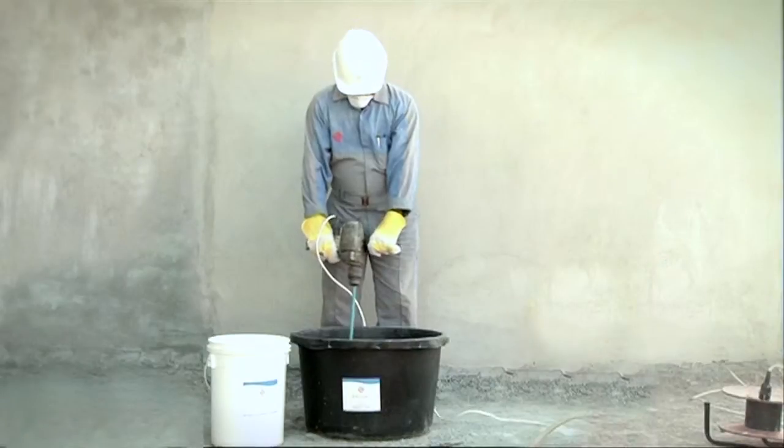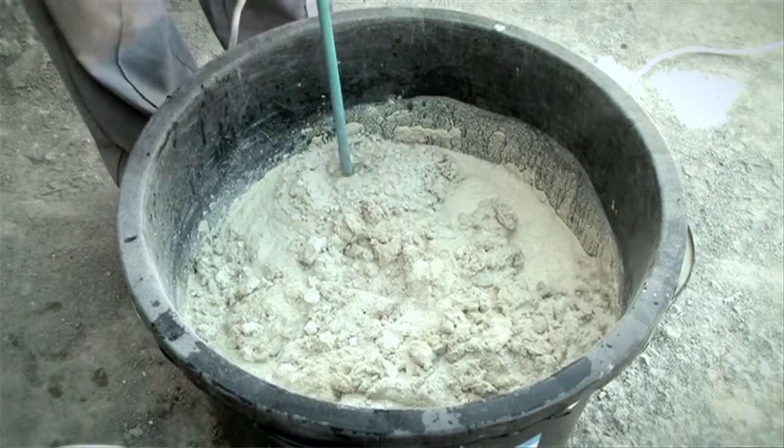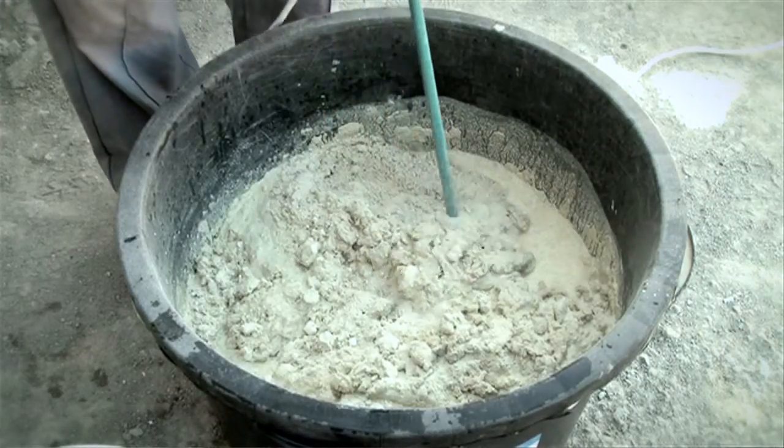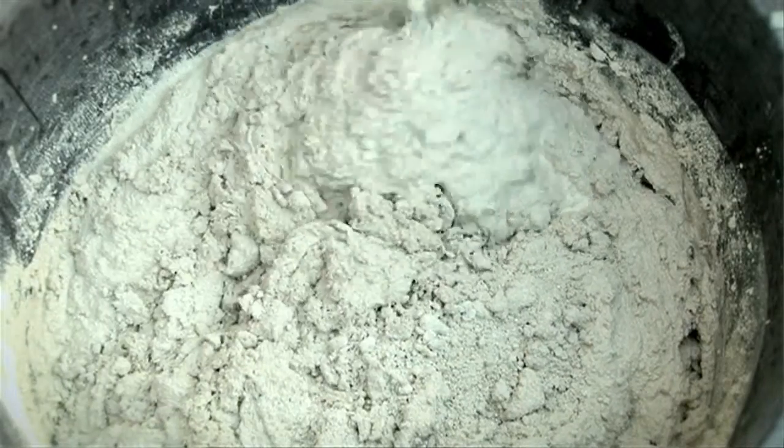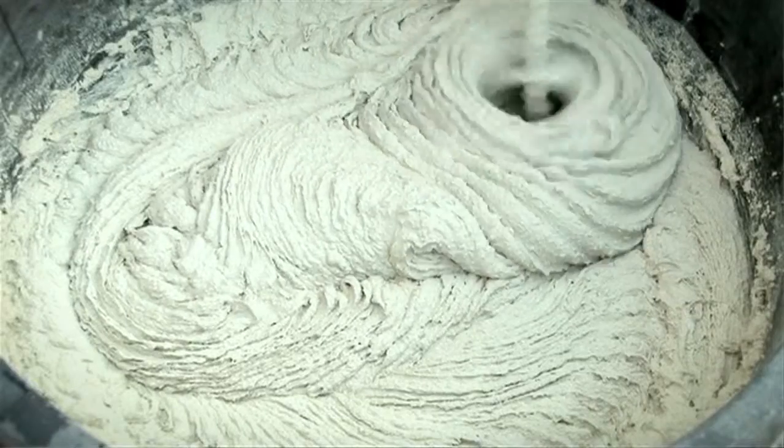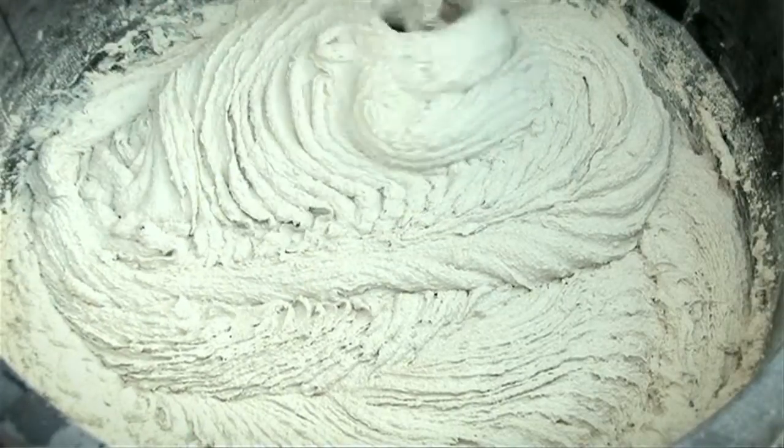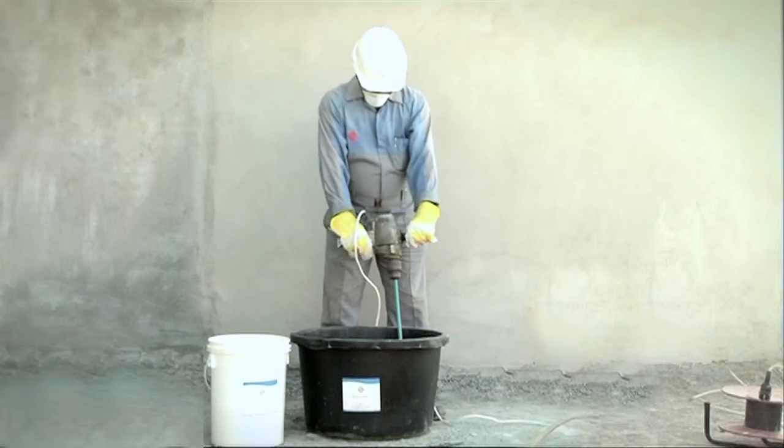To ensure a homogeneous and uniform mix, an electric agitator must be used. Once mixed, allow to stand for 5 minutes and mix again before applying.